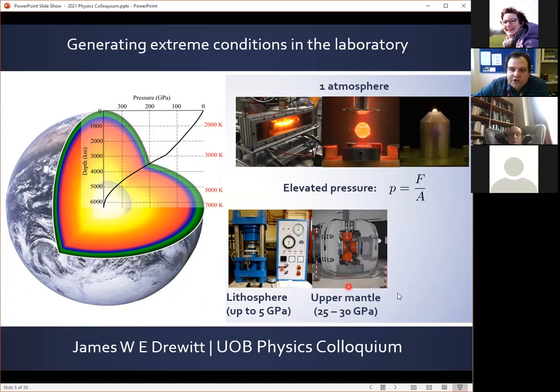And at higher pressure conditions, for example, those corresponding to Earth's upper mantle, we can use a larger scale multi-anvil press shown here, where we can access upper mantle conditions of 25 to 30 gigapascals and 2000 Kelvin, for example. But the conditions within the very deep Earth, at the core-mantle boundary, for example, are in excess of 100 gigapascals and 3,000 or 4,000 Kelvin, and the pressure in the center of Earth's core is 360 gigapascals.